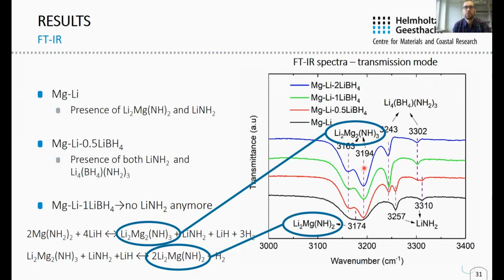This result may explain the results from the thermal analysis, where samples with lithium borohydride present a single peak and the pristine sample presents double dehydrogenation peaks. Therefore, I assume that the reaction pathway may be altered by lithium borohydride addition. Presence of Li4BN3H10 is confirmed in all lithium borohydride containing samples, and the formation of this phase can lead to reduced activation energy in these samples. In the sample with 0.5 mole of lithium borohydride, both LiNH2 and LiBH4 are present. And in this sample, it is seen that the amount of lithium borohydride is not sufficient to react with all LiNH2, since we still see this phase.